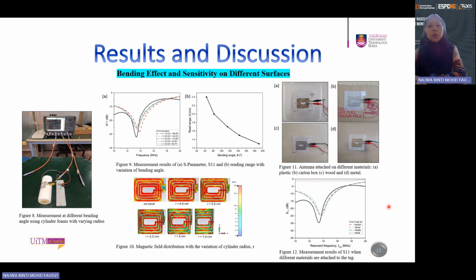This is because when the bending angle is increased, the antenna's accessible surface area is reduced, which consequently reduces the induced magnetic field in the tag antenna and reduces the tag reading range. We can also see from these results the distribution of the magnetic field from the simulation here. As the bending angle is increased, the distribution of the magnetic field also decreases. So that is the reason why the tag reading range is reduced with the increase of the bending angle.